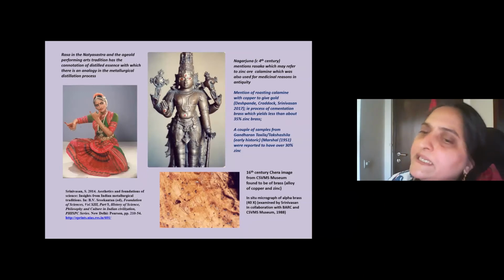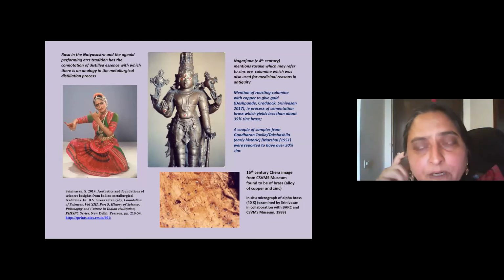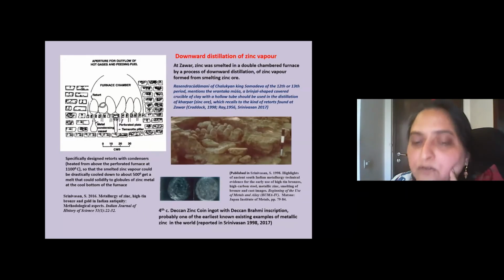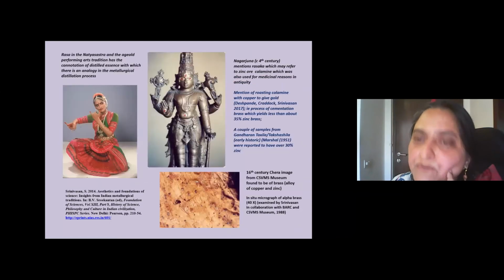But what was interesting is that you do find a couple of samples from the Gandharan site of Takshashila, or Taxila as we call it, which is reported also by Marshall in 1951, which were reported to have over about 30% zinc. And so it is quite likely that they were actually using metallic zinc, because to get so much zinc into brass, which goes past the alpha solid solution, implies that you had to use metallic zinc. So as you see that zinc ingot over there, you would have had to alloy that to the metallic copper in this case.